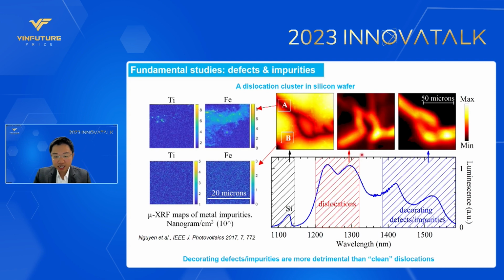And this is an example from silicon. We investigate the characteristic light emitted from the impurities inside the materials. Then we study the spatial distribution of these defects and impurities. We can see that the impurities are often decorated along the dislocations and reduce the performance of our materials. The message from this figure is that the decorating impurities are much more detrimental than the dislocations themselves. So if you want to improve your silicon material quality, get rid of the impurities first before thinking about the dislocations. So that's the message that we find.